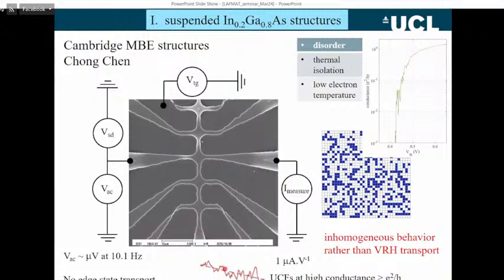What we also see is that when we're at high conductance, when we've got lots of carriers in, we tend to get conductance fluctuations. So the system is behaving in a very different way to what we were expecting. It goes over to conductance fluctuations.